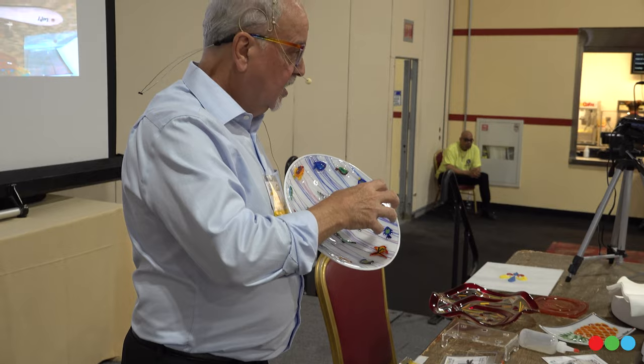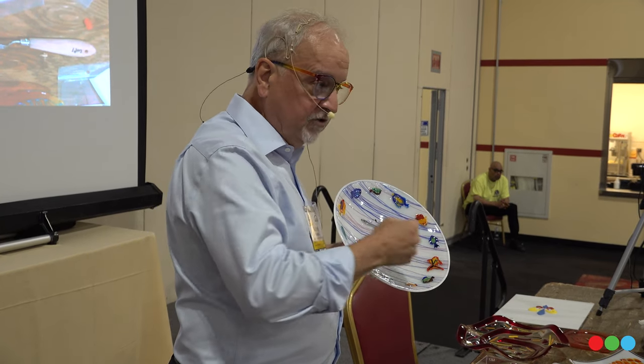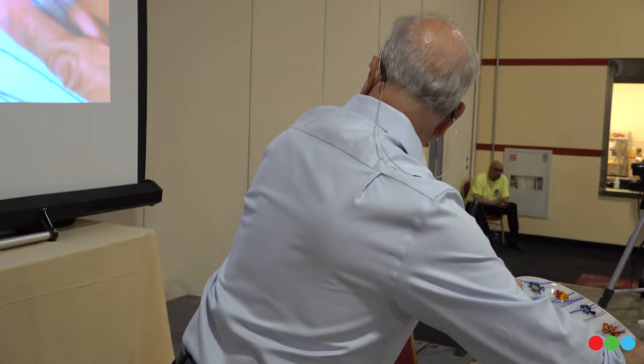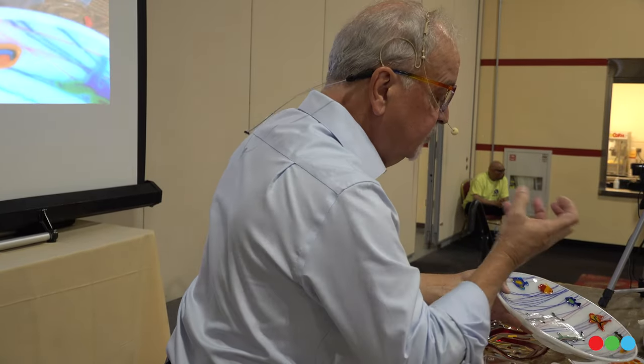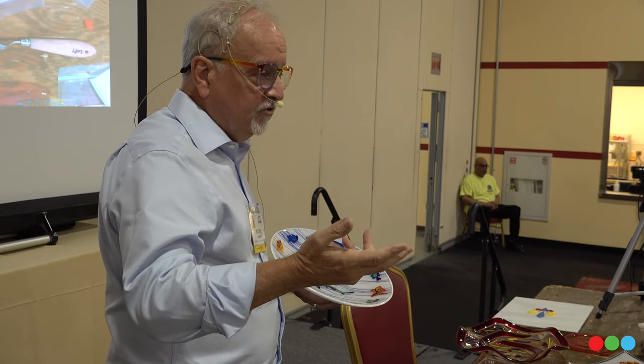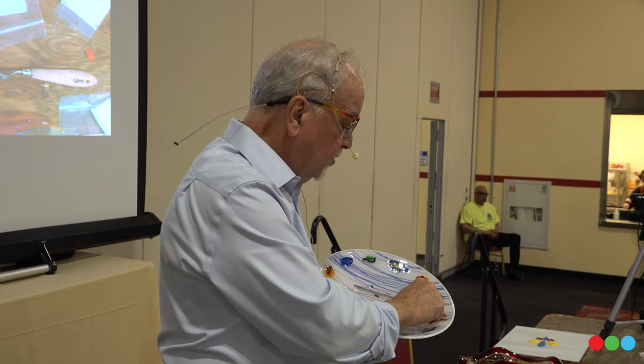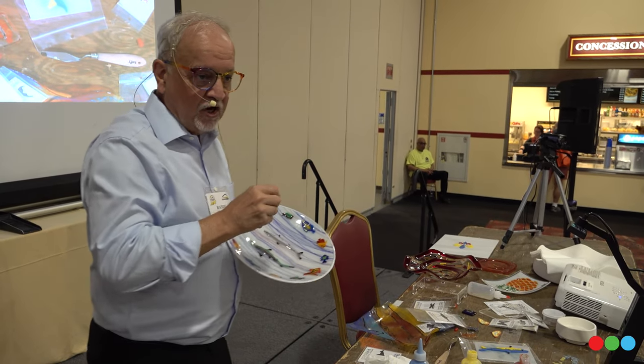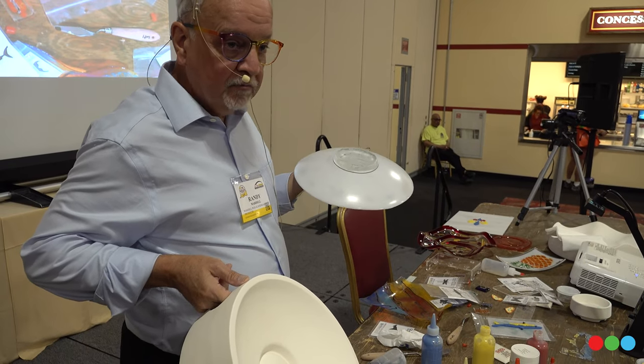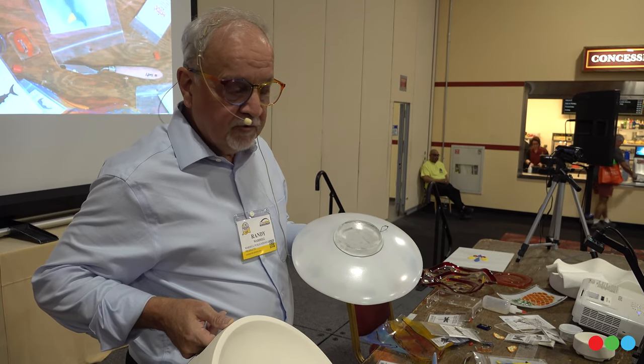Wafers are a single cavity, and then you use that single cavity as your design start point and build your design around it. Here's a dragonfly — same thing. I put one dab of the regular goo under each wafer to hold them all in place, put that in my kiln and fired it. In this case I fired it at 1,380°F — that's my contour temperature. Takes it down nicely. You can feel the texture — some of the goo is still raised around the outside edges, which gives it a nice raised quality feel.